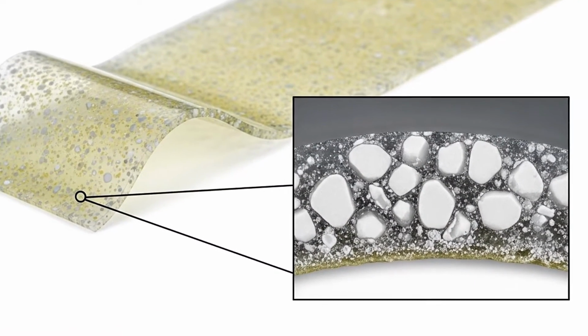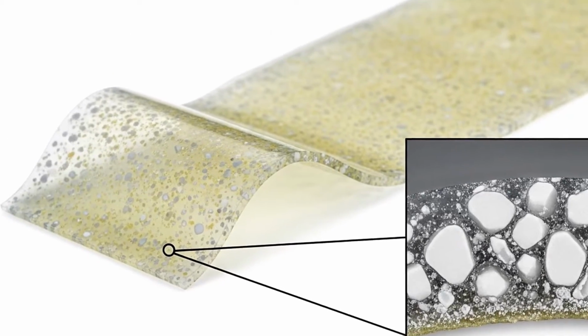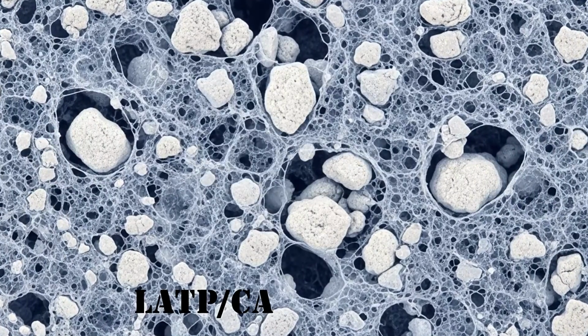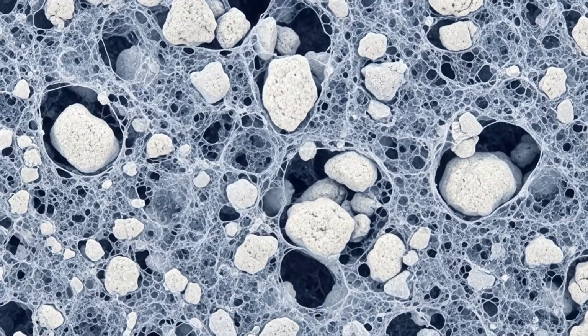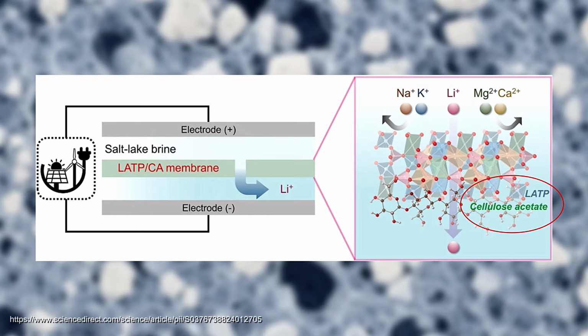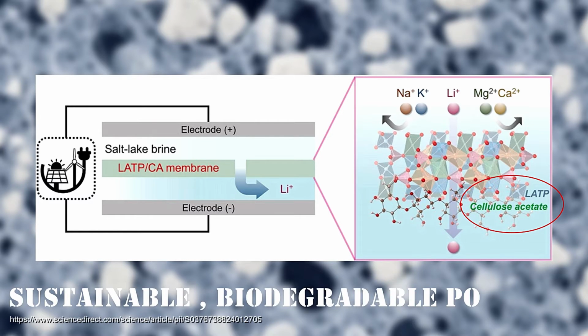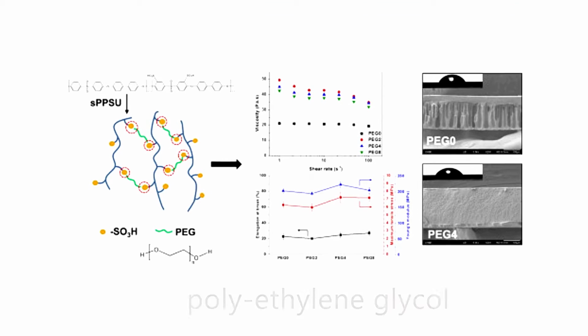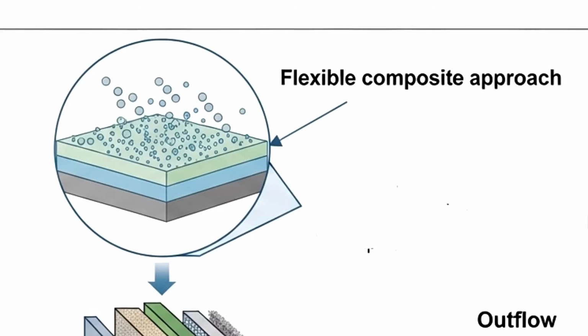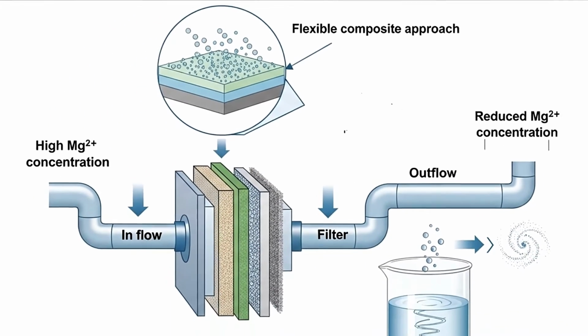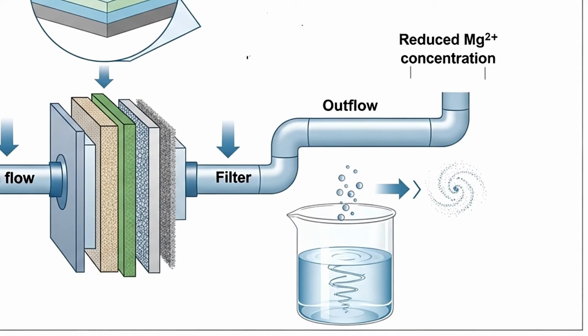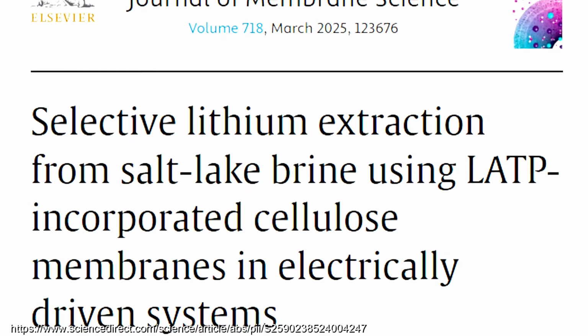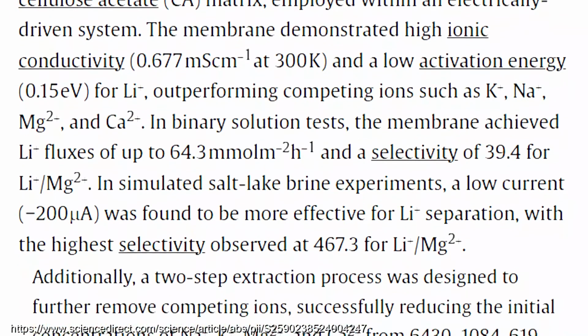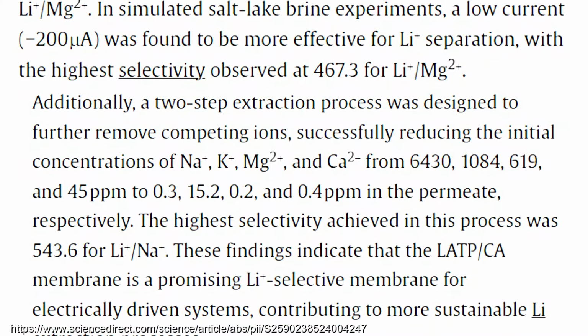Researchers started integrating these selective ceramic particles into flexible polymer matrices. For example, the LATP/CA membrane embeds the selective LATP ceramic into cellulose acetate, CA, a sustainable, biodegradable polymer. They even added polyethylene glycol, or PEG, to increase flexibility. This flexible composite approach delivered the goods. Tests showed magnesium 2+ concentrations reduced by 300-fold, and after a simple two-step electrical separation process, they achieved incredibly high purity, with lithium/sodium selectivity reaching 543:1, all in just 12 hours.